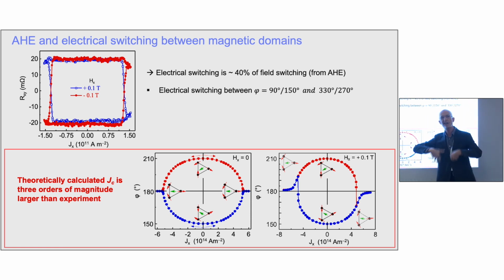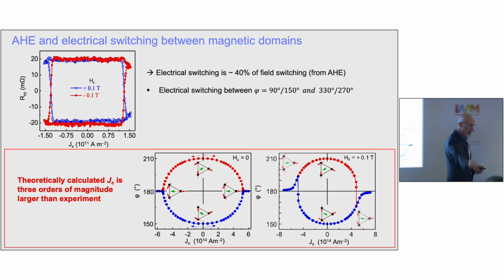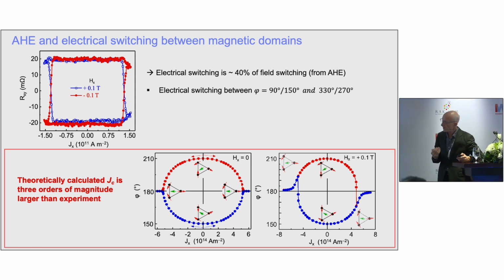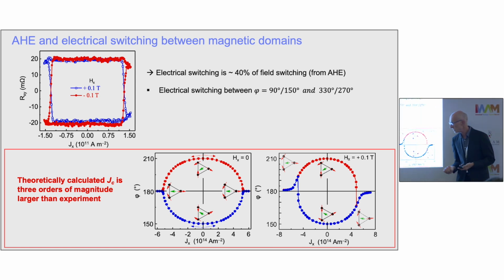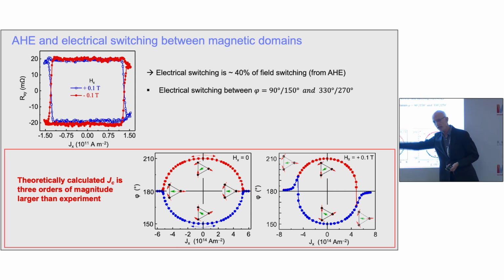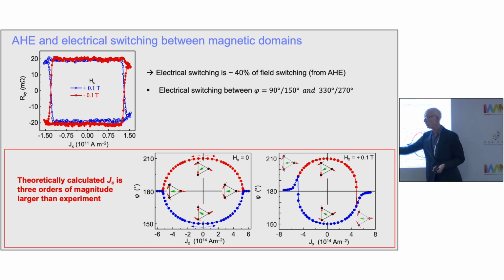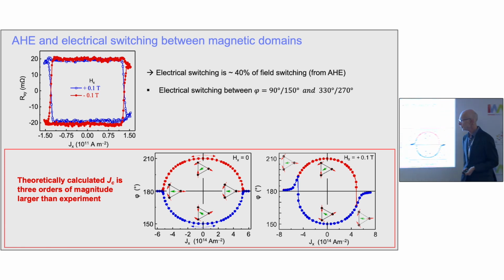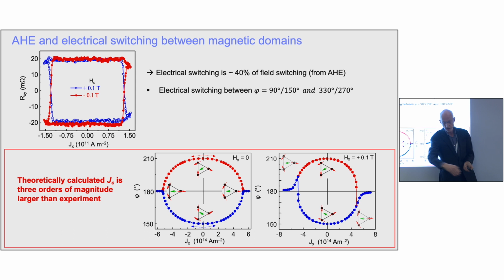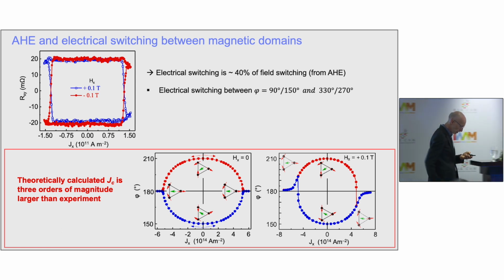So he's calculating that you generate a spin current from the spin Hall effect in this, I didn't really say it, it's a layer of tungsten. We grow on top of this manganese-3 tin. The spin current diffuses into this material, applies spin torques because spin angular momentum is conserved, and causes these moments to rotate in this fashion. It rotates from a low energy state to a high energy state in the absence of field. And so when you remove this current, it can go back to these 2 equivalent states. In fact, you end up then with no signal.